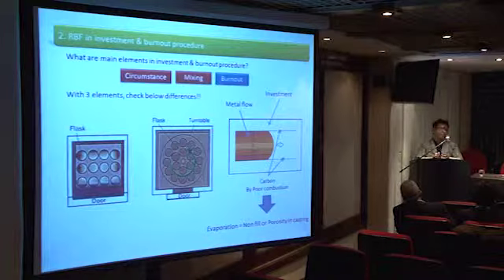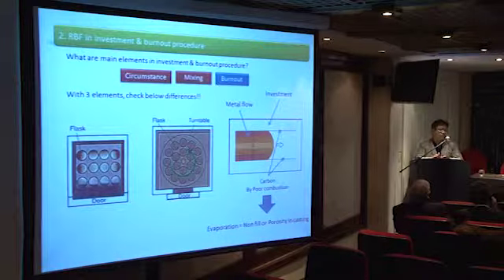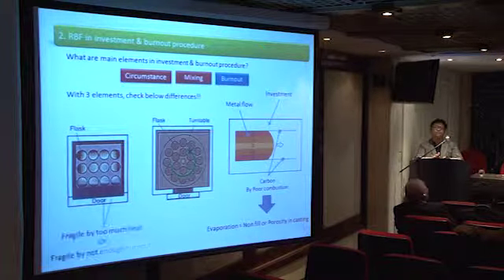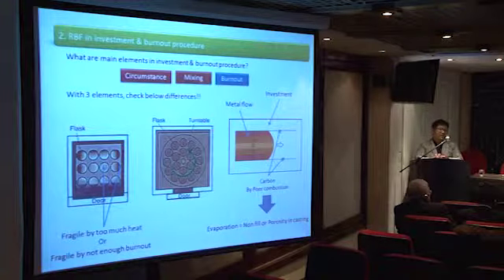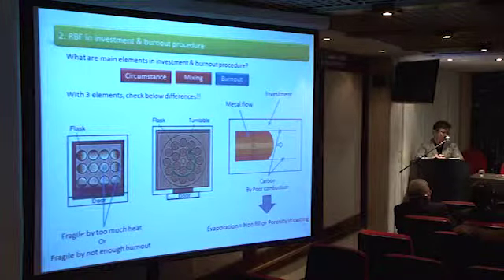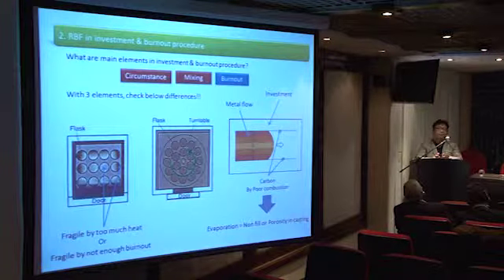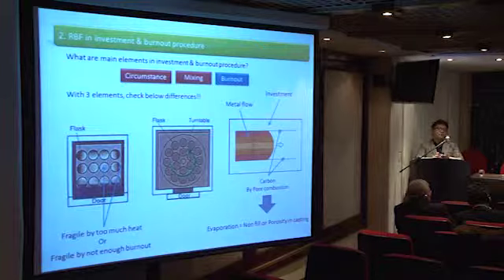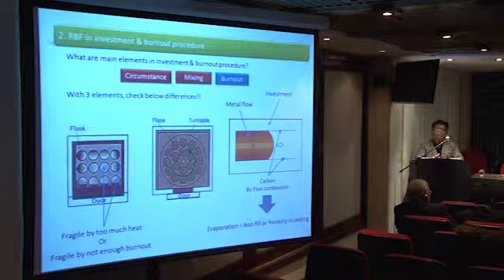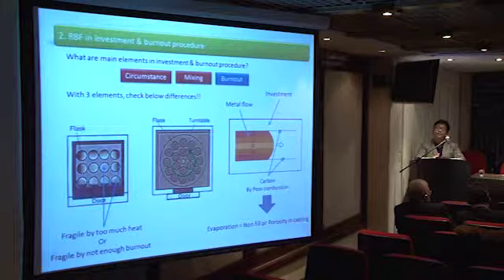That is why if you don't have this, there will be either gas porosity or shrinkage porosity, which is caused by the gas kicking out or the evaporation of the metal itself. The reason why we need even heat temperatures in all the stages, especially in the hardening, as I explained, is that the investment powder is very fragile. If you have too much heat into it or not enough burnout, you'll have the same thing, which is the evaporation coming in, where you basically have a non-fill or a porosity in the casting.